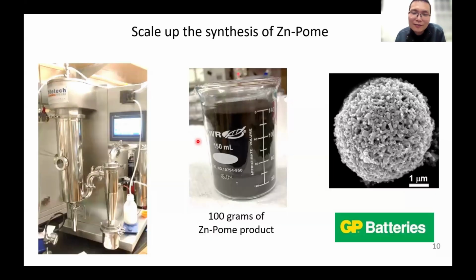We used a very complicated method to synthesize this initially. Then we worked with a company, GP Battery, to develop a much more scalable and simpler way to synthesize the same structure. This is a spray drying process, and we can produce 100 grams at a time. In the past, we could only do 100 milligrams. So with this scalable approach, we can now look further into commercialization, and that's what the company has been doing.